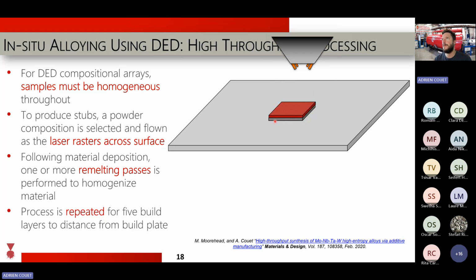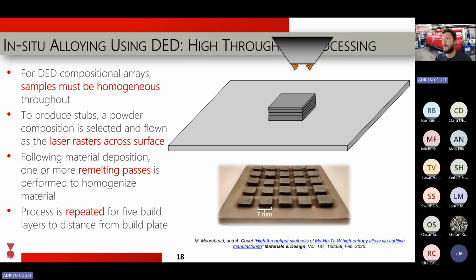And we can, for instance, print small squares or small cubes like that. One of the issues we can have is that we don't necessarily melt everything because some powders have a higher melting point than others. So we tend to reglaze, as we say, or remelt using just a laser with no powder so that everything is melted. And then we do that again and again and again, and you build a few millimeters of a cube like that of a given composition, and you don't change the composition. And you end up with those plates. We call them Lego plates, where you have a build plate and you have your material on top.